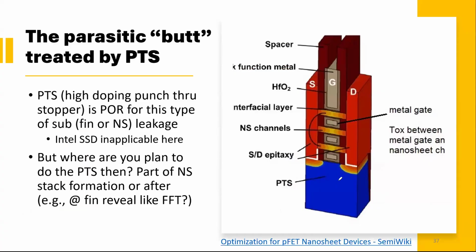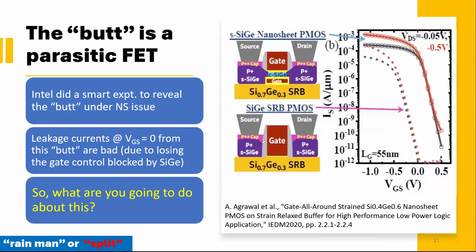This butt problem looks like this. Actually, I want to show you that this graph is better. I think Intel did a very smart experiment to reveal the butt problem under nanosheet, and I think it's a wonderful experiment. What they did is you have some silicon germanium under it, and this is a normal planar PMOS. You have a 30% PMOS, so the leakage is going through here. This is your leakage path. They use a planar structure to simulate the nanosheet. And nanosheet, on the other hand, there's here, pretending you have one stack.